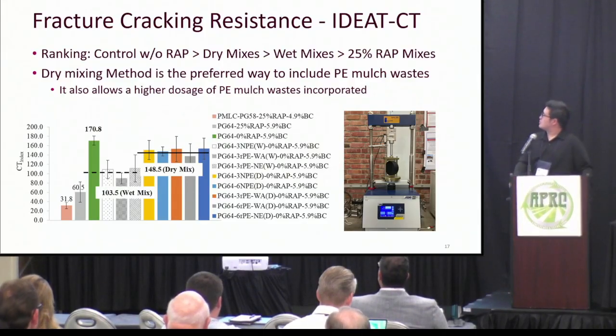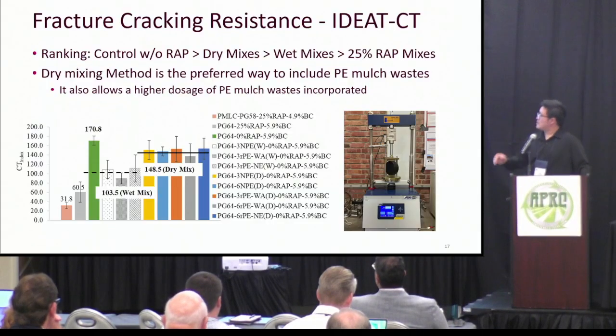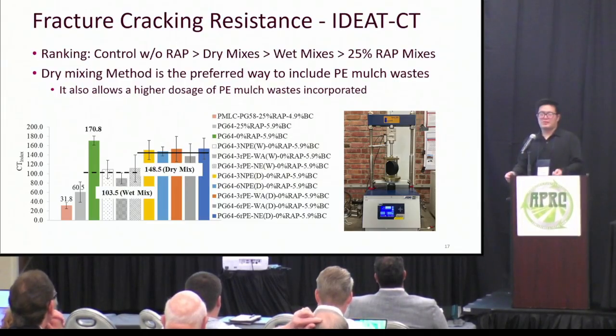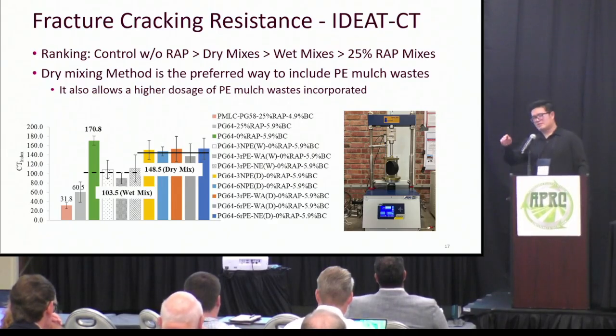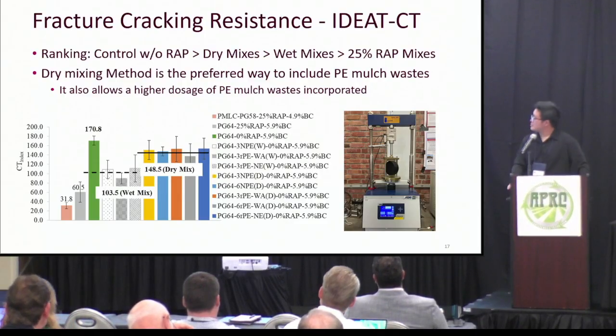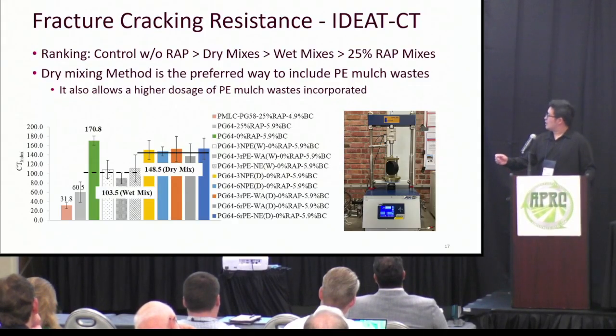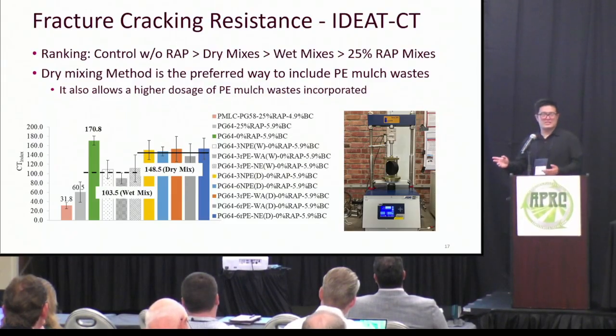So if you look at the fracture cracking resistance, it's called the IDEAT-CT test. The dry mixing method performs better than the wet mixing method, and the ranking from highest to lowest is the control mix without RAP or plastic, then the dry mixes, then the wet mixes, and the last is the 25% RAP mix. So the dry mixing method is the preferred way to include PE mulch waste, and it also allows a higher dosage of PE mulch waste. But this is just for the cracking resistance.